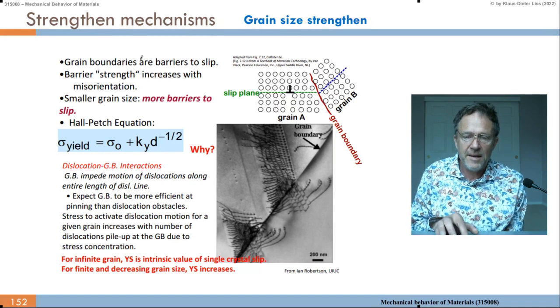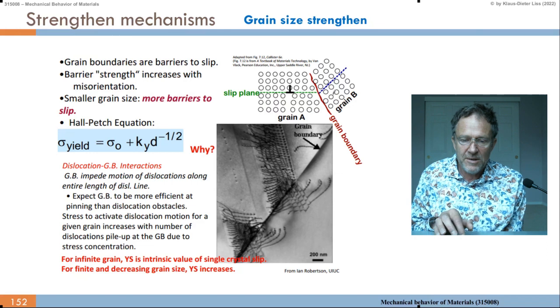So for grain size strengthening, here's another model. We have the slip plane, we have the grain boundary, and we have to bring the dislocation around the corner, and this costs energy. So you see they may pile up. Here we have one dislocation, it piles up. The next dislocation piles up there. And if you do that further for many, they all pile up here like a traffic jam. And eventually some are transmitted through the grain boundary. And the next pile-up is here.